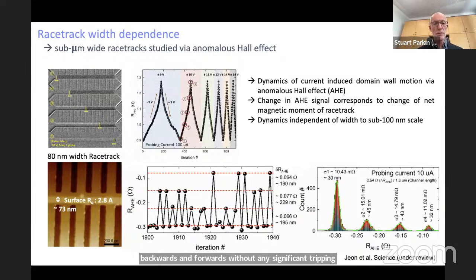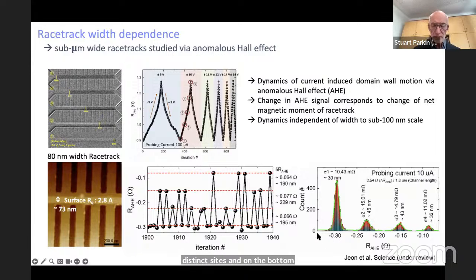This allows us then to position, using these nanosecond long current pulses, the domain wall anywhere along the racetrack. And we've just shown in the bottom middle, you can see we positioned the domain wall at one of 4 distinct sites. And on the bottom right, you can see that we can do this many, many times, and we can see that we can position a single domain wall to a positional accuracy of about 30 nanometers, and we can certainly space them apart better than 100 nanometers. So this is a very important step towards a fully fledged racetrack memory.